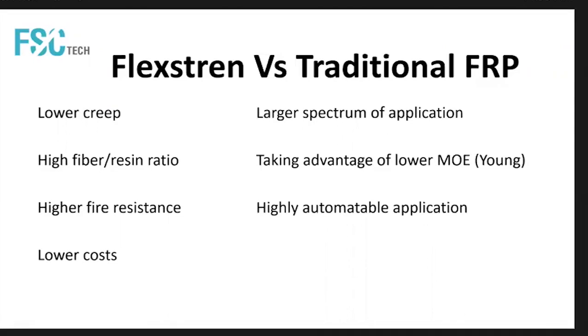You get a very high fire resistance with this system because, even if the resin burns completely, since the wrappings are overlapping, the friction between the various wrappings is not loosening anything. Everything stays together. Even if the resin burns completely, you don't have any loss of tensioning. And if you are using fibers like basalt, up to 650 Celsius, you basically do not have any derating.